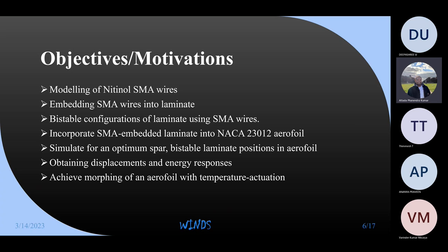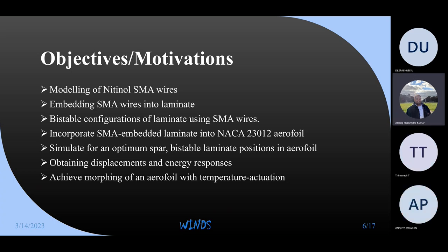Yeah, it's an interesting point you brought up, because it also gels well with what she was talking about, adaptive buckling. There are certain things that could be considered a problem for a long period of time, especially by the industry, because of their conservative nature, that could actually be opportunities. So you try to utilize them to see how you can benefit going forward. The other example that you talked about, anti-symmetric or any asymmetric laminate for that matter, even helicopters have used anti-symmetric layups sometimes to get the extension twist coupling to a beneficial utility.